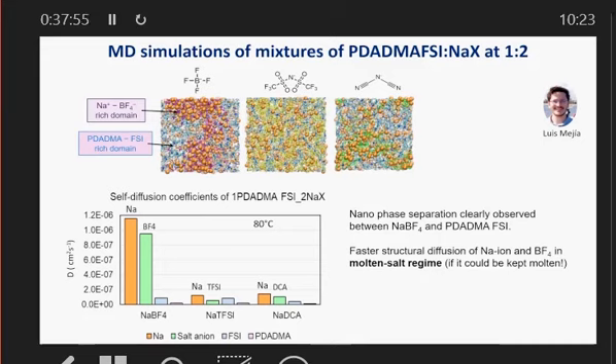But interestingly, when we actually went and measured the diffusion from mean square displacement, this is all theoretical, computational, the diffusivity, this is now centimeters squared per second, was significantly higher in the system. So if you could keep the system molten, you'd have a really high sodium diffusivity. Big if. And even the TFSI and the DCA showed high diffusivity compared to just the FSI system. And so this gave us some promising idea about whether we can control the sodium transport with mixed systems.